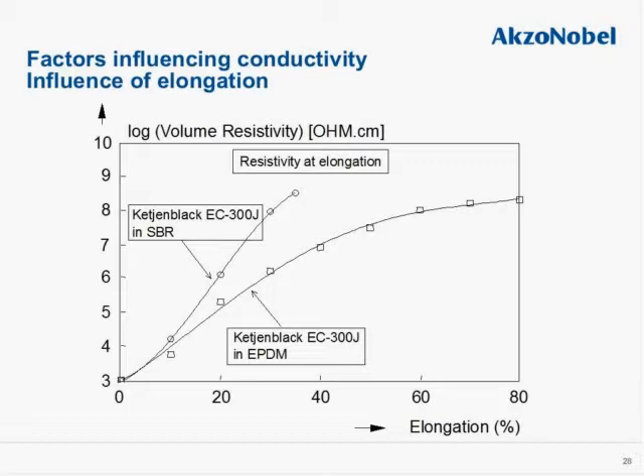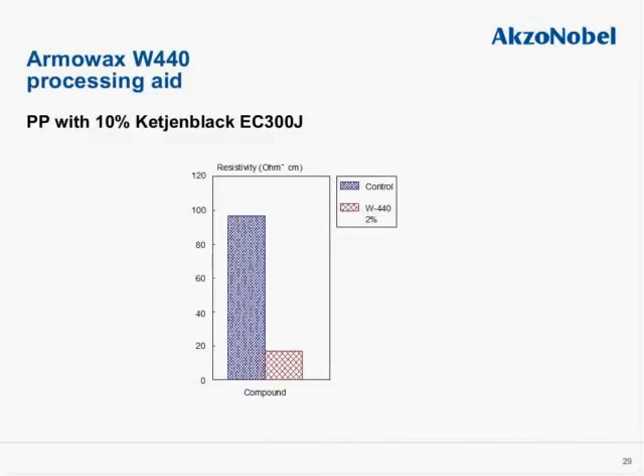As soon as the stress ceases, the conductivity is going to go back to the original. So in cases where the elastomer is going to be used in tension, a formulator will need to keep this in mind and accommodate probably with a slightly higher load of Ketjenblack in order to keep the conductivity intact over a longer elongation in terms of percentage-wise. I mentioned earlier that dispersion is key, and the equipment that is recommended for Ketjenblack will be a twin screw extruder. Another way for ensuring a good dispersion is by using dispersants, some sort of processing aid.